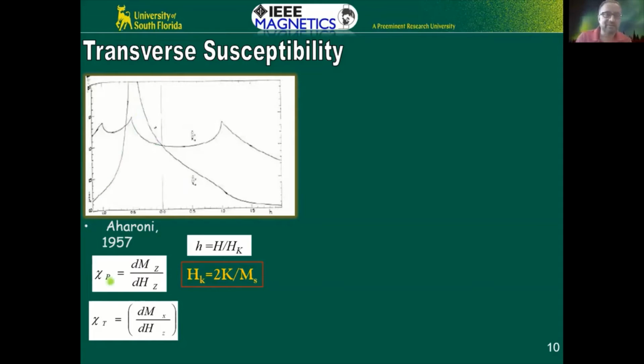Now he pointed out that in the transverse configuration, in addition to the switching field here, you also see two other peaks which are symmetrically located on either side, and it turns out that they're located at the anisotropy field. Remember that anisotropy energy is one of the most important fundamental energy scales in ferromagnets. So this is a way of identifying the anisotropy field directly by looking at these sharp peaks. That's exactly what we did.